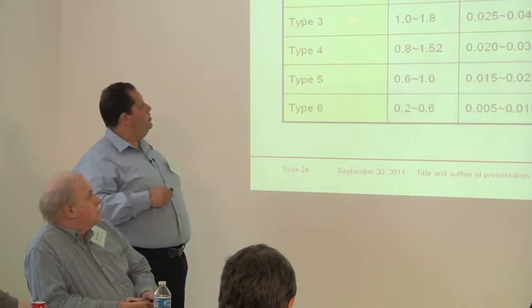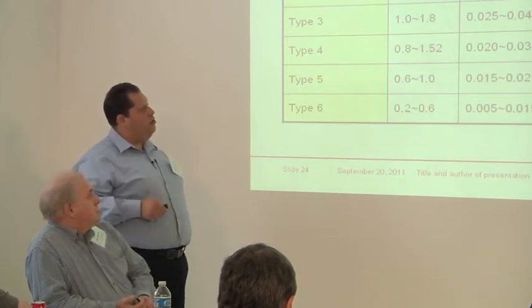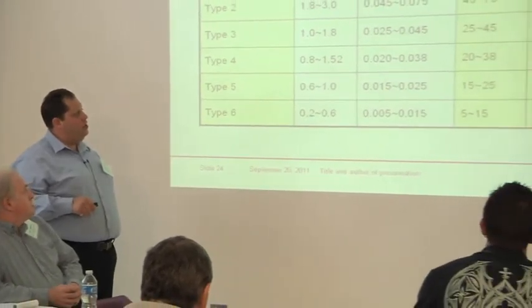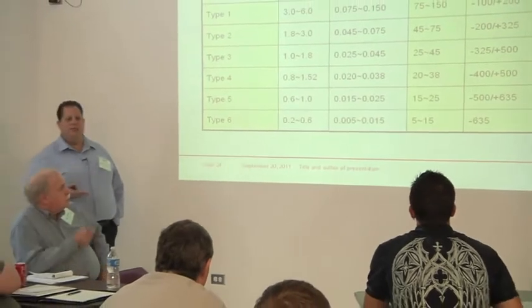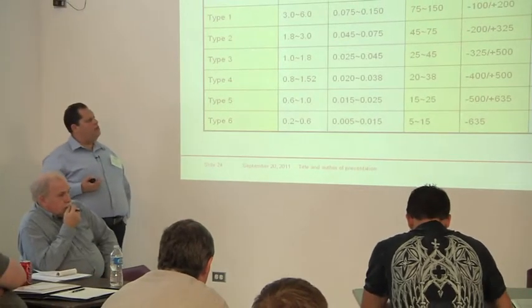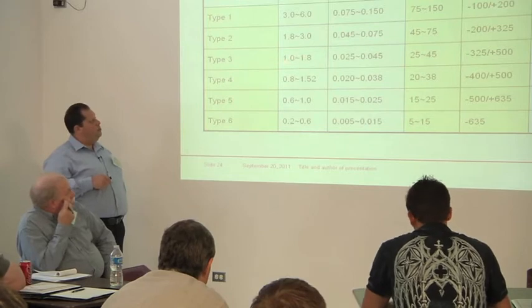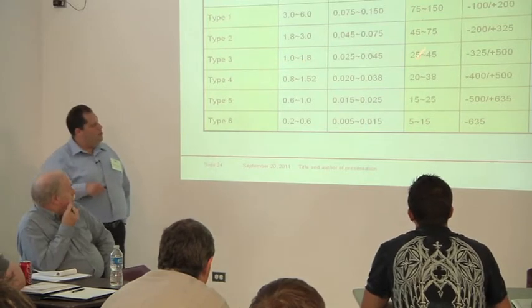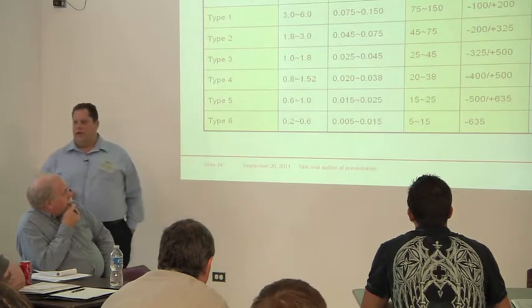If you look at the particle sizes, most of us talk about microns. Most of them are between 25 and 45 microns. These are the mesh sizes - if you think about sieves or meshes, those are the mesh sizes that we'd use. Talking about in mils, between 1 and 1.8 mils. And 90-plus percent of the particles are in that range.